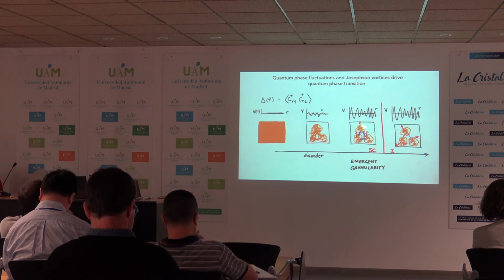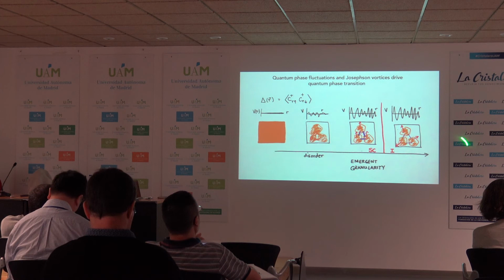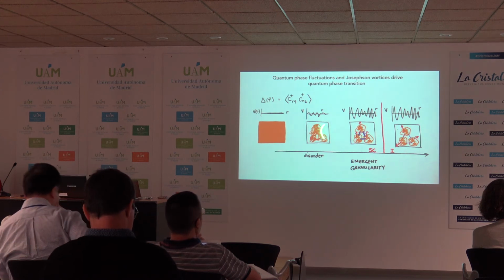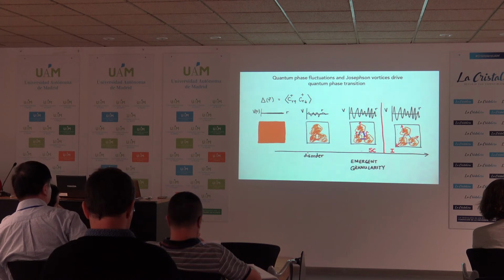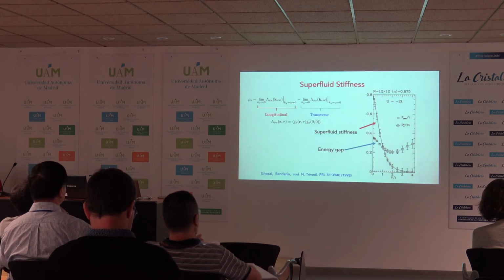On the superconducting side, they are well aligned through the Josephson coupling between these patches, but if due to increasing disorder or whatever your tuning parameters, the Josephson coupling is weakened, then you go into a regime where the quantum fluctuations are able to destroy the coherence and give you an insulator. So that's really the picture of the superconductor-insulator transition.